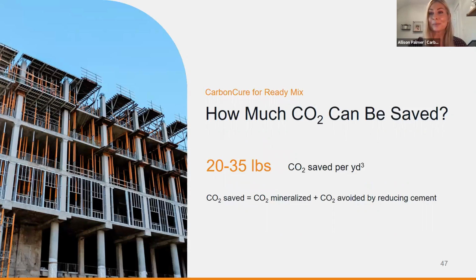So how much CO2 can be saved? At the end of the day, this process reduces approximately 25 pounds per cubic yard, but that figure can vary quite a bit depending upon the mix design. The first way we calculate this figure is through that 1 pound that I mentioned that is injected, chemically converted, or in other words, sequestered.